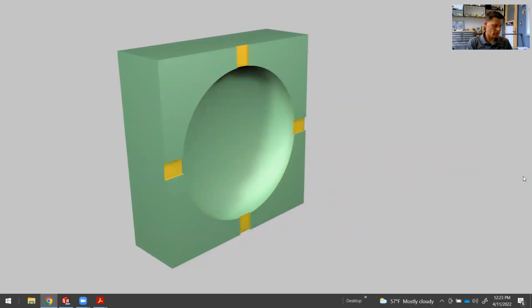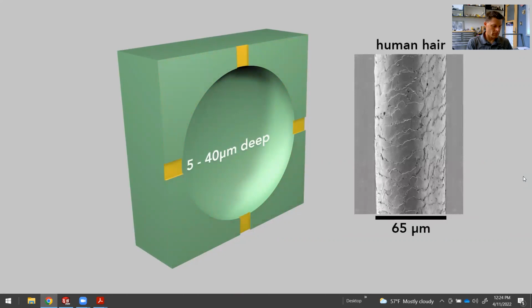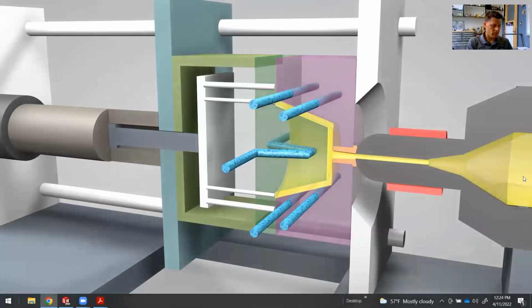These vents are channels ground into the landing surface of the mold. They're very shallow, between 5 and 40 microns deep. The plastic, which has the consistency of warm honey, is too viscous to flow through the narrow vents. To speed the plastic solidification, coolant, typically water, flows through channels inside the mold just beneath the surface of the interior.